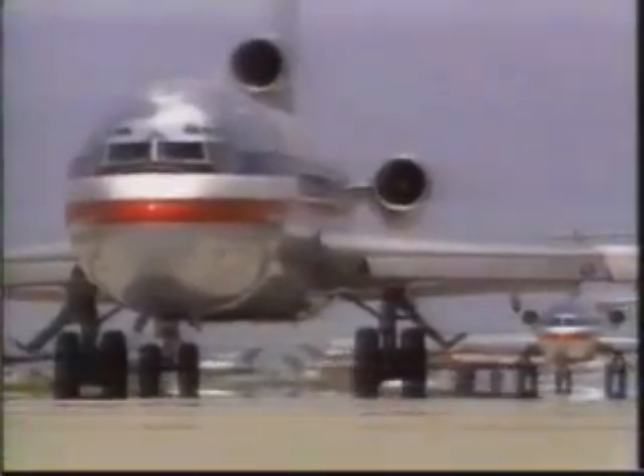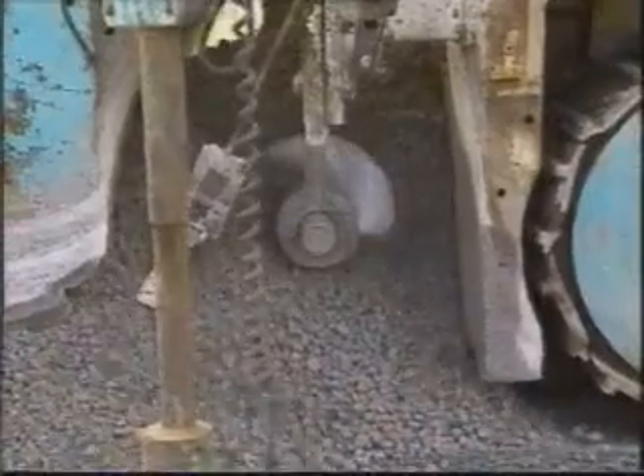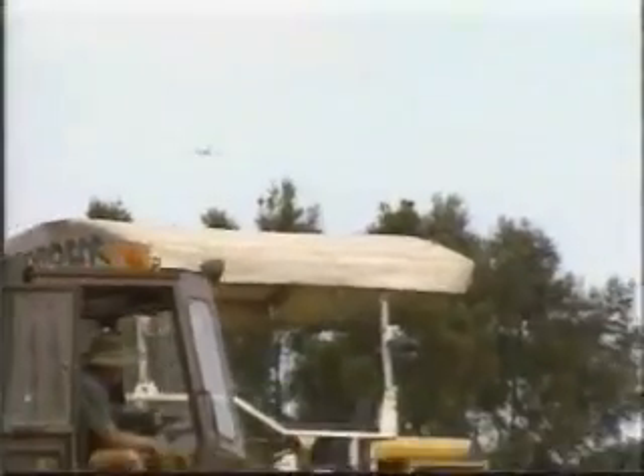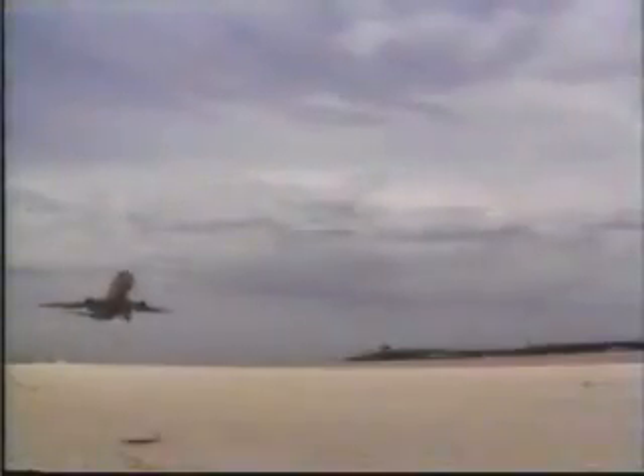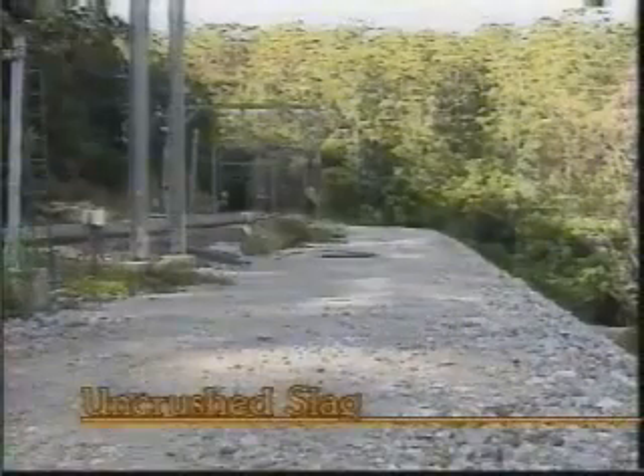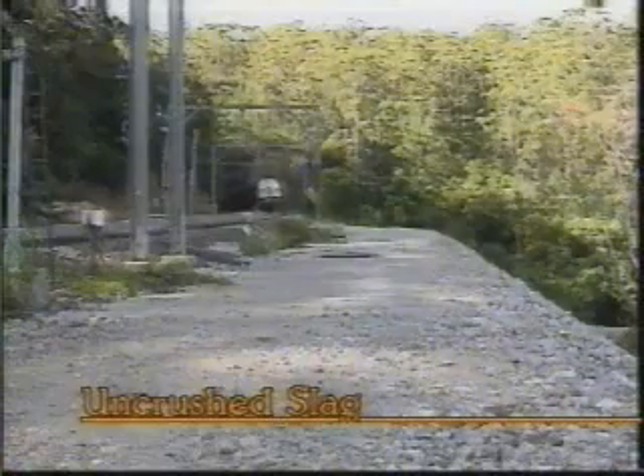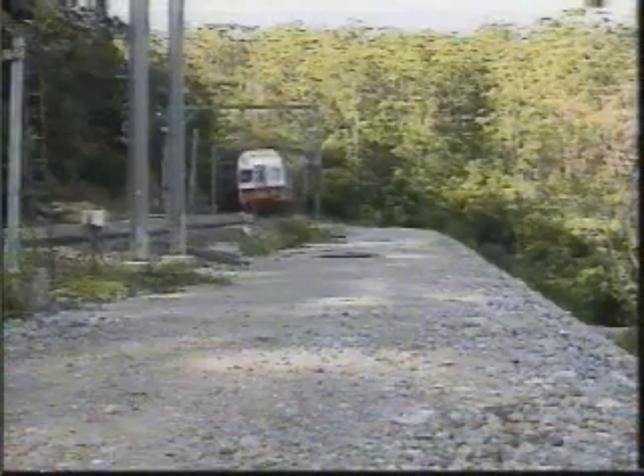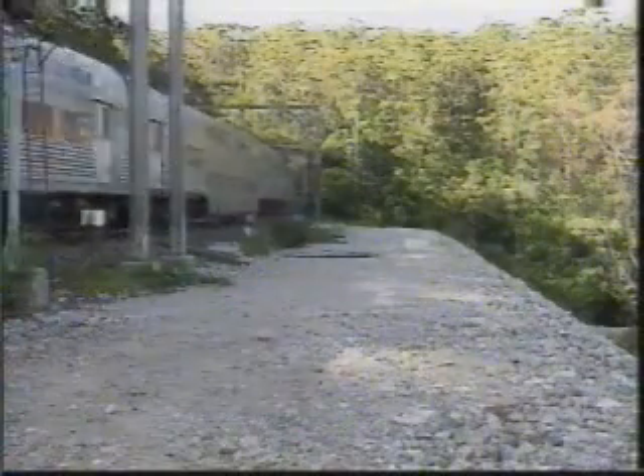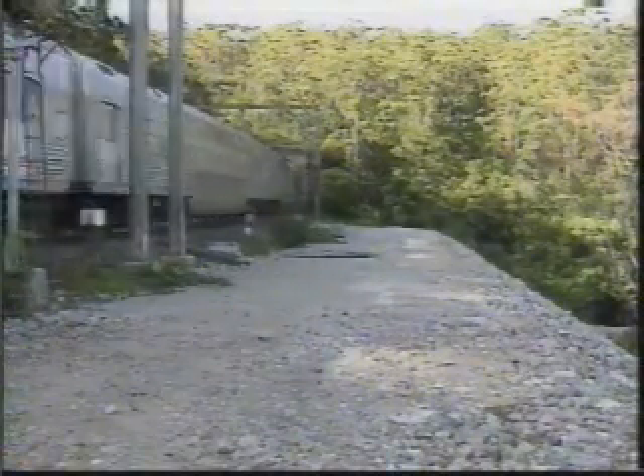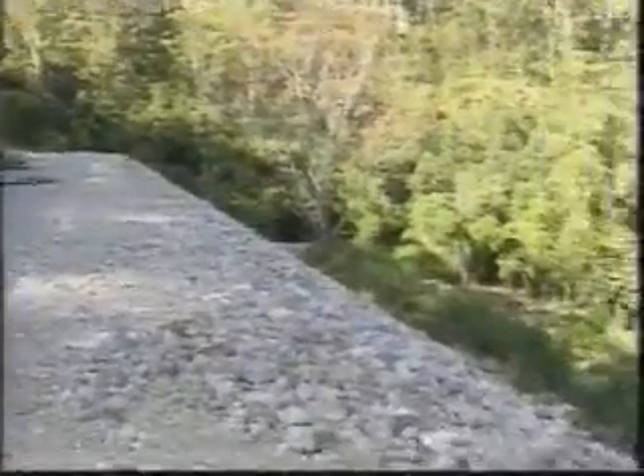Overseas experience has proven that where it is available, blast furnace slag is a preferred material for airport runway pavements. Extensive field testing by the Australian Federal Airports Corporation concluded that blast furnace slag is highly suitable for airport runways. Subsequently, slag was used in the construction of the third runway at Mascot, Sydney, and continues to be used in further construction projects. Uncrushed slag is also an ideal material as a select fill for civil engineering projects. State Rail in New South Wales nominated uncrushed blast furnace slag as a preferred fill material and has used significant quantities to stabilise embankments in mountainous slip areas.